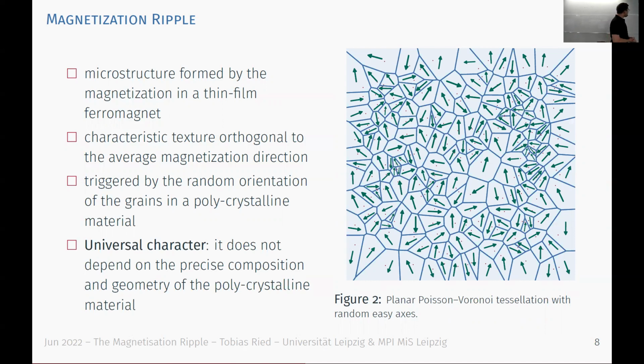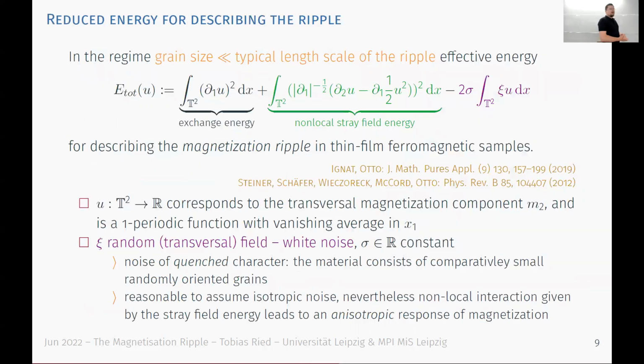And what I want to work out and show you how to do is a universal character of the phenomenon that this polycrystallinity leads to, namely these fine oscillations, the magnetization ripple. Namely that the ripple doesn't really depend on the precise structure of your grains, so the precise composition or geometry of the polycrystalline material, but really essentially just on one parameter, which I will show you next. So that's the goal.